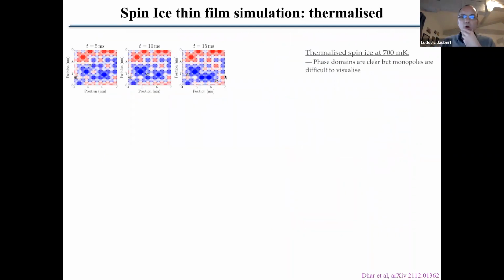And now how to measure monopoles, how to see monopoles in spin ice? Because the problem is that if you look at the phase map, this is what a phase map of a spin ice would look like in a thin film. And as you can see, these minus and plus charges are the magnetic charges, they are excitations. Everywhere else is in the ground state, so that's 2 in, 2 out, and the minus and plus are the magnetic charges. And as you move with simulation time, Monte Carlo time, which to some extent represents real dynamics, the magnetic charges move around, but even if they move around, you can see that it's very difficult to distinguish them from the background. Here in simulations, we know where they are, but if you only look at the phase map, it's nearly impossible to see where the magnetic charges are. So it's not very good to actually see the magnetic monopole.